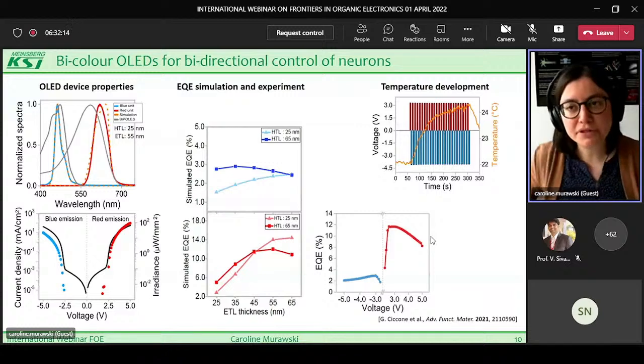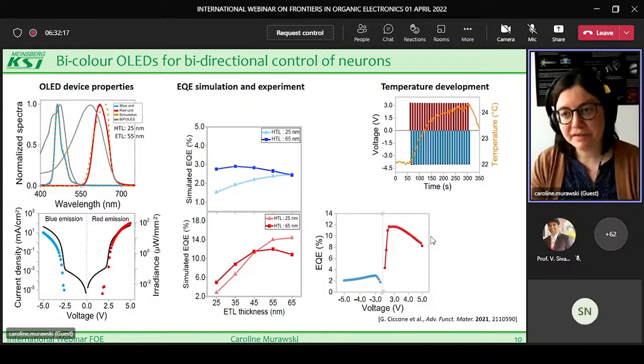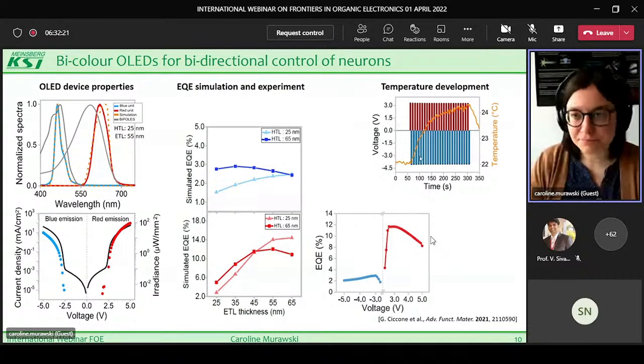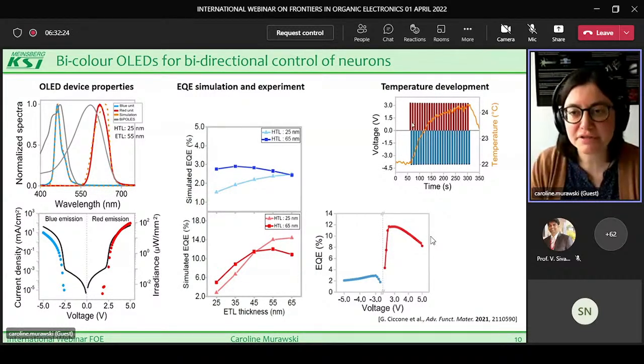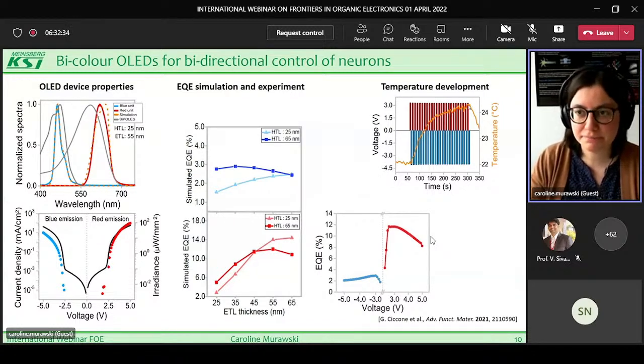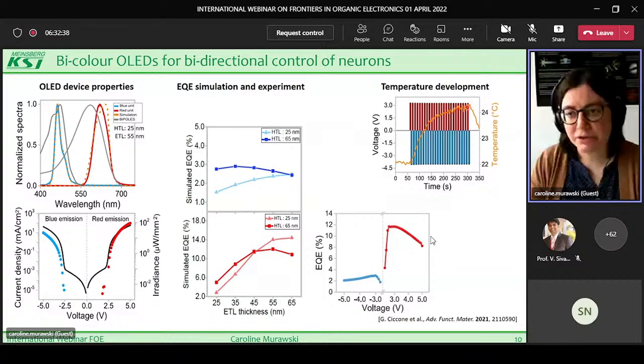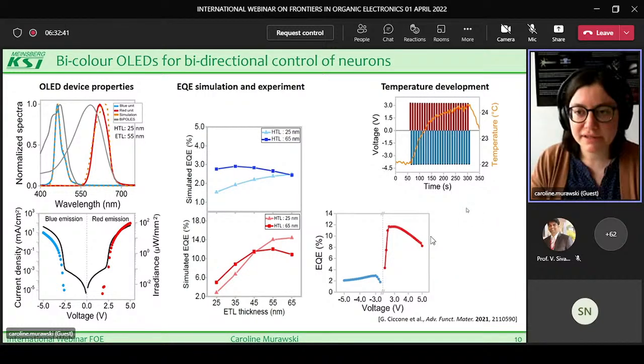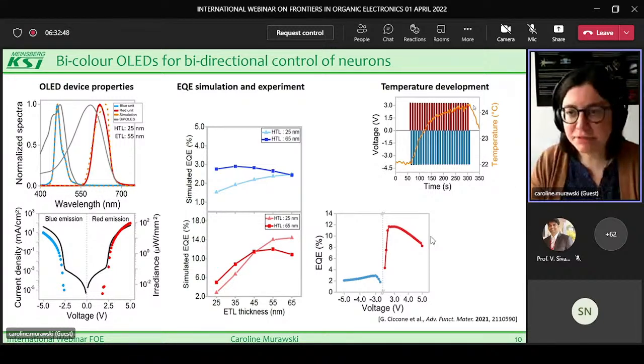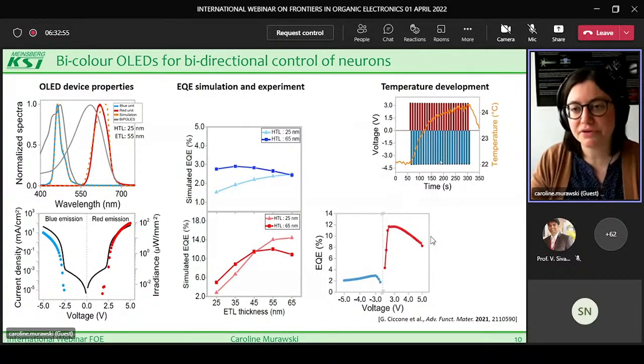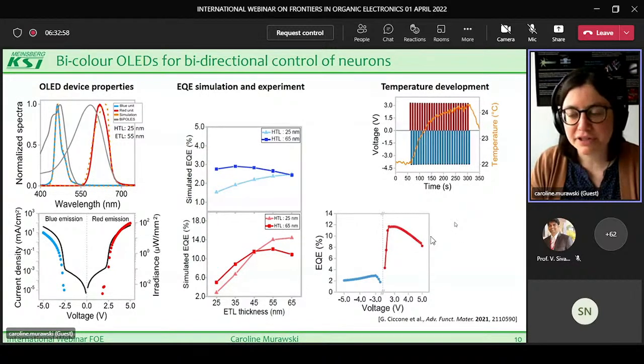As I said previously, it's also important to look at the temperature development of the devices, and we measured this for a sequence of positive and negative bias, so either red or blue emission of the device, where the device was driven with 5-second pulses alternatingly, and we had an increase in the temperature of around 2 degrees during this time. That's still a little bit too much if we want to get in close contact with cells, but this could be improved when improving the device performance, and especially also using different driving schemes, because this is really like turning or keeping the devices on for like 250 seconds.